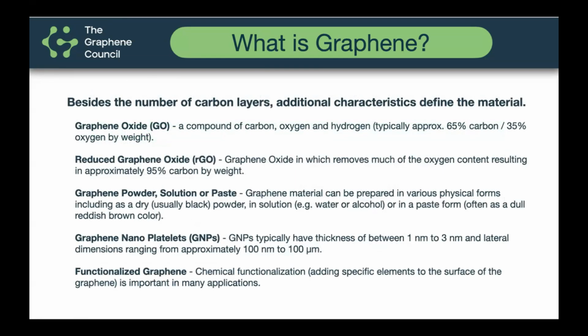Graphene oxide contains about 35% oxygen by weight. It could be 30 or 40%, different levels. And graphene oxide, or then reduced graphene oxide, behaves differently than graphene nanoplatelets or graphene flakes. For example, pure carbon graphene is hydrophobic and is very electrically conductive. Graphene oxide is hydrophilic and is no longer electrically conductive because of the oxygen content. So even though it's in the same family of material that we consider graphene writ large, it behaves very differently. And this is one example of why choosing the right type of graphene for your particular application is a little more complicated than maybe some people assume.